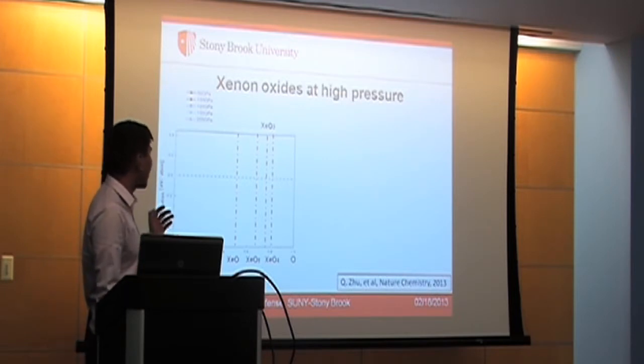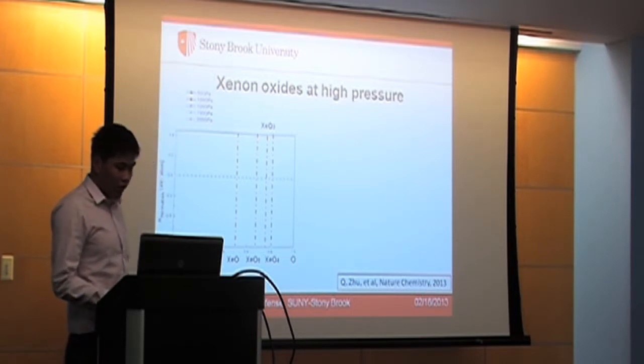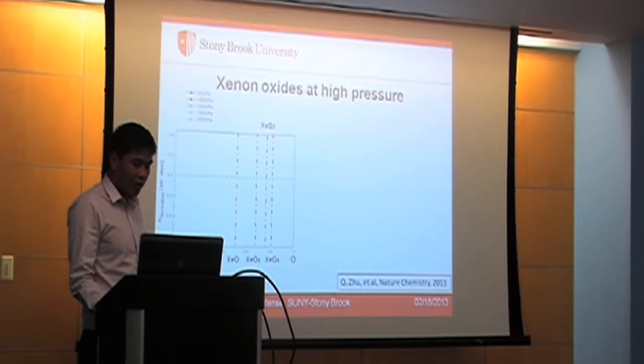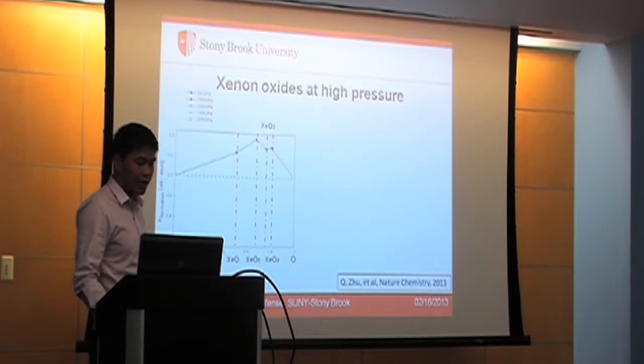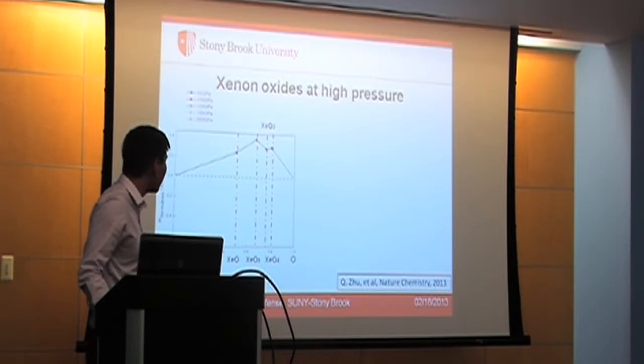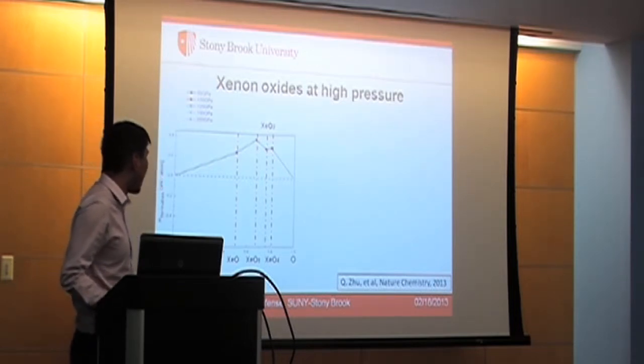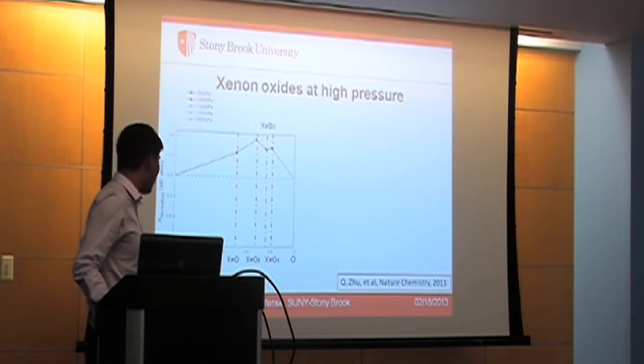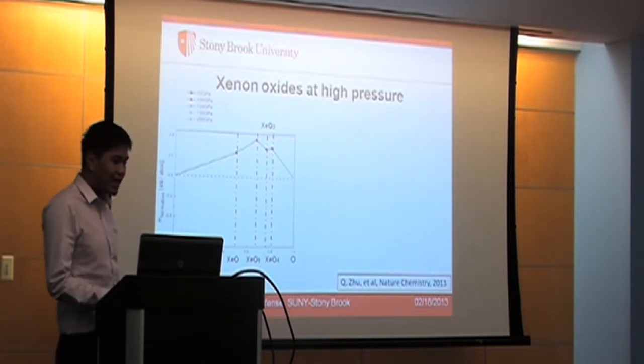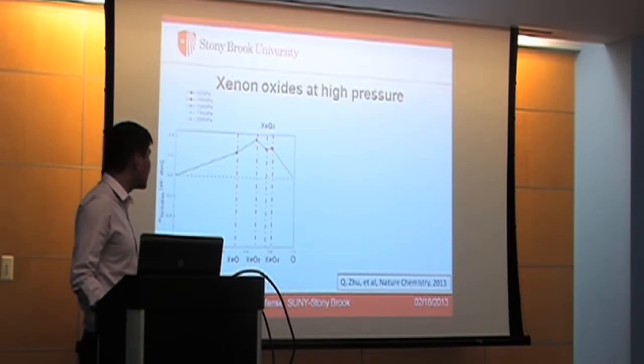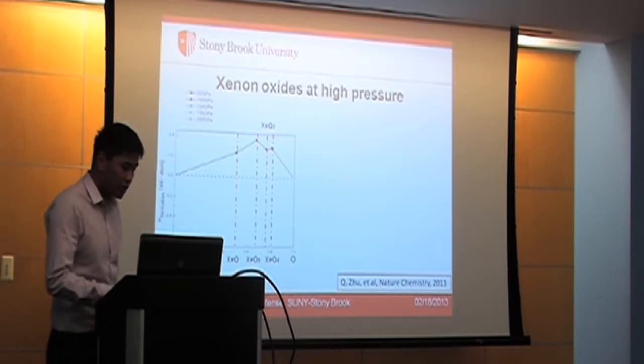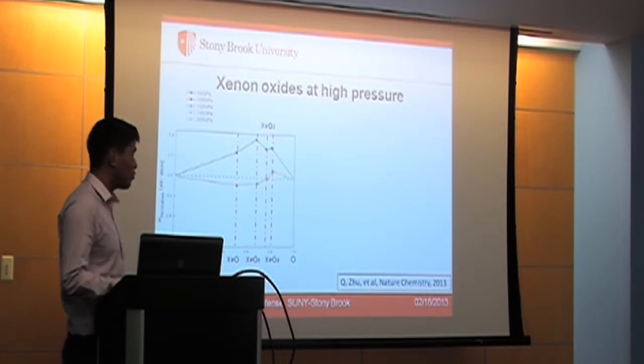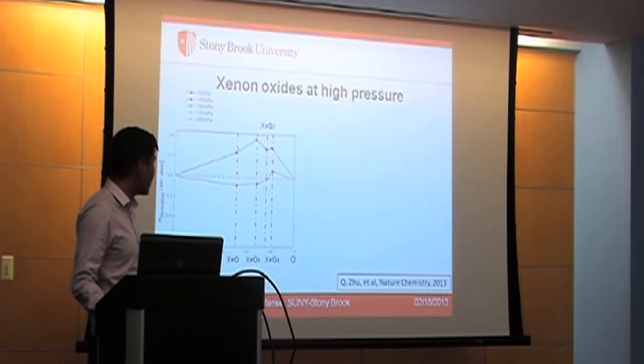Remember, we have studied 4 different chemical compositions from XeO to XeO4. When we analyze our results under relatively low pressures, like 50 GPa, we found that all of these energies are above the composition line of elemental xenon and elemental oxygen. It indicates that these compounds would be unstable. However, if we apply pressure around 100 GPa, which is exactly the pressure scale of the Earth's mantle, we found that XeO and XeO2 become stable.